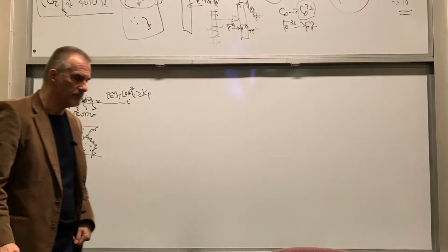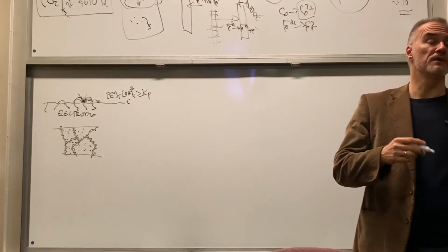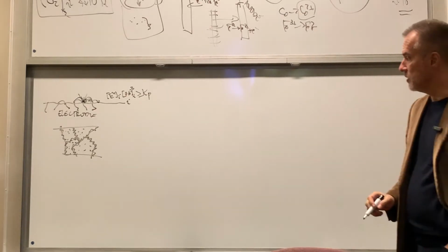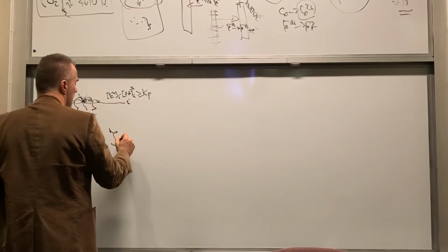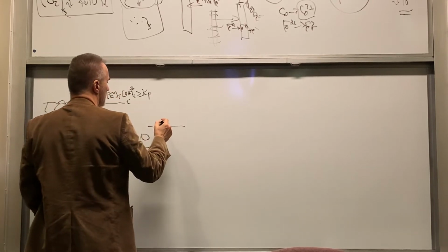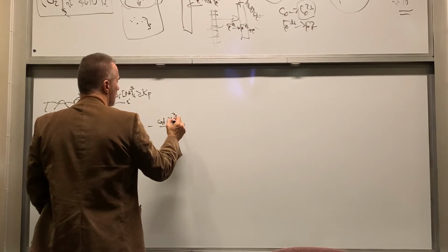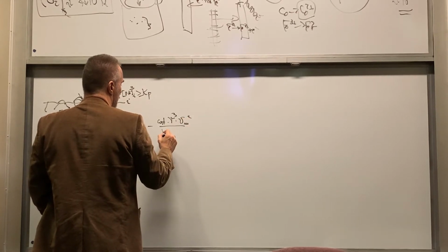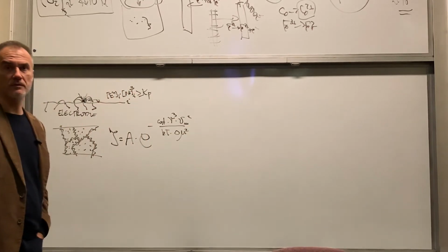All right. Now, when we talked about nucleation, we didn't talk about nucleation only because of electrodeposition. Generally, the nucleation phenomenon occurs whenever you grow a new phase. But what we really discussed is that the nucleation rate in terms of thermodynamics, J, is some constant times e to the minus, and then we have some numbers, I'm going to say constant, but then it will be gamma to the power 3, then molar volume to the power 2, kT, and delta mu squared, if we remember.